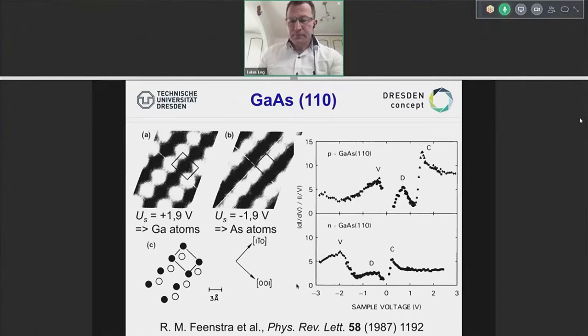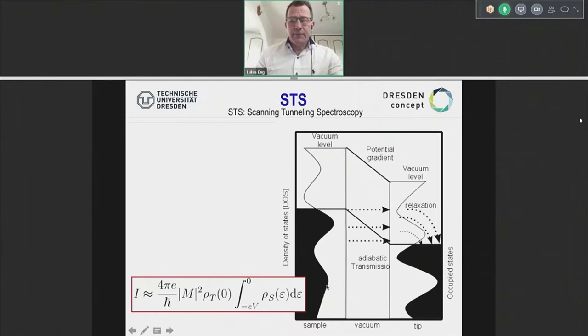Well, a cartoon that we could make up from this is taking the left half and the right half, where the densities of states are shown here, separated by a certain barrier, which is the vacuum barrier that we see here between these two. And in fact, if you just level this up, imagine these are two lakes, like for instance for power stations, if you level this up, then more electrons can flow to the right. If you level up this one to the right, more electrons can tunnel to the left. And that's exactly what happens when you change the bias voltage in STM. So that means we are able to really see these densities of states. Or in other words, we see exactly where the energy levels of a system are.